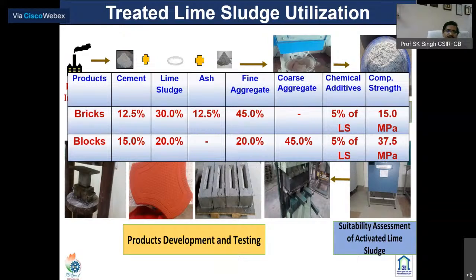One small brick has been made with 12.5% cement, lime sludge about 30%, boiler ash about 12.5%, fine aggregate 45%, and a cheap chemical additive we have developed, and we can achieve a brick compressive strength of about 15 MPa. If we reduce the cement content to 10%, we can achieve a compressive strength of 10 MPa, as well as water absorption of about 10 to 12%. So it will be as per our requirement. In paver blocks, we have used cement 15 to 17.5%, and with 15% cement and coarse aggregate, we have achieved 37.5 MPa.